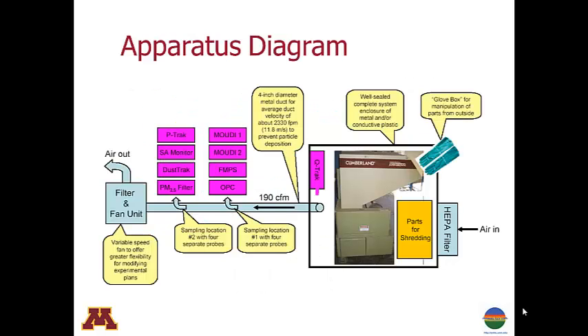This is a diagram of our apparatus. The air was pulled into the enclosure containing the granulator through a HEPA filter by a fan unit. A pair of gloves like those used in glove boxes was inserted into the enclosure to allow the test plaques to be picked up and placed into the granulator. We were able to measure the temperature and relative humidity inside the enclosure using an instrument called a Q-track. The air was drawn from the enclosure through our test duct at a rate of 190 cubic feet per minute or 320 cubic meters per hour. We sampled the air from the duct at two locations using a variety of aerosol instruments.